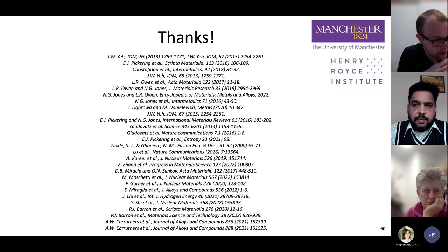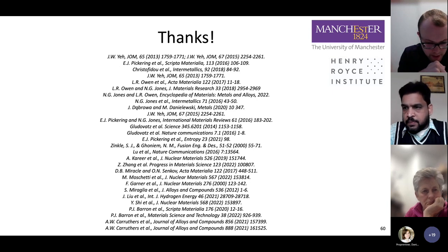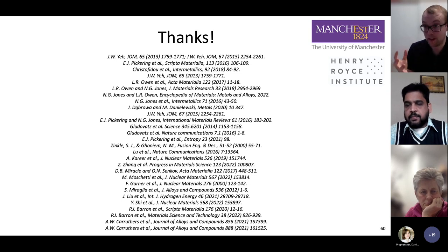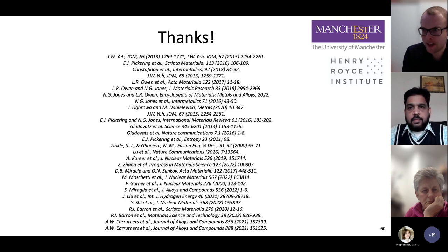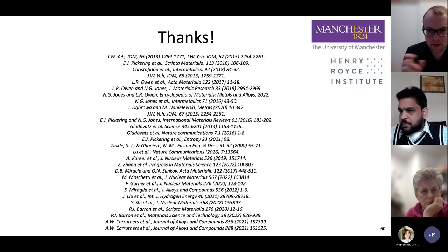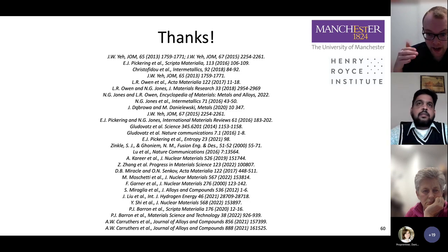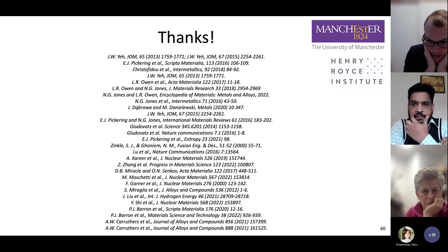I know that Dave Armstrong at Oxford has done some historic work where he's looked at the effect of nitrogen pickup in some of these alloys, and you can form totally different phases based on quite small amounts of nitrogen. If you're not careful, you would think that they are not nitrides, but some other phase, if you haven't measured the nitrogen. So it becomes really tricky, in particular with those refractory alloys.